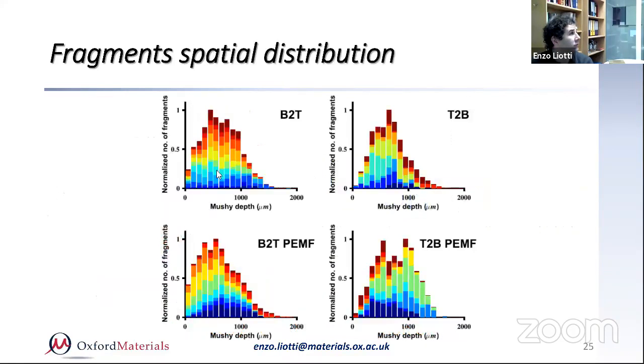The other thing that was interesting is the distribution of the fragments within the mushy zone. Somebody would expect that most of the fragmentation takes place at the tip, within the tip region. Actually, we found that there was almost a log normal distribution in all the experiments, showing that fragmentation takes place more or less to a depth of a few hundred micron in. That peak is always the same, and that is independent from the top to bottom or bottom to top. So that tells us something about the mechanism.